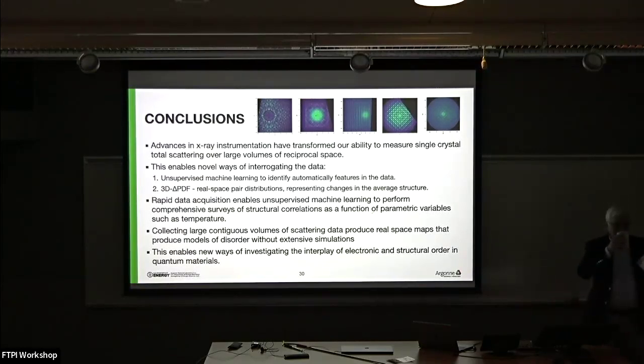So Bragg glass is a distinct phase of matter, so of course it's extremely exciting to establish it. But now that you've done this machine learning, can you then go back and look at the Bragg peak to see that you have a power law cusp, not a Bragg peak? Our resolution is not enough to actually be able to fit the power law tails, so that's what you're asking.